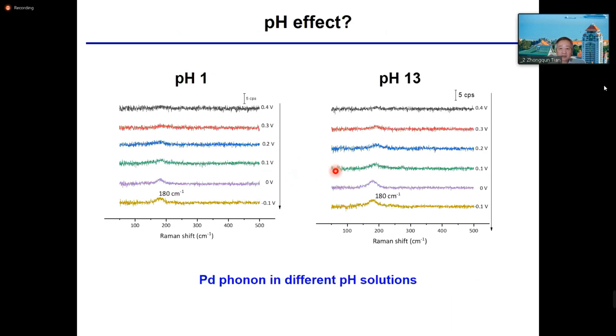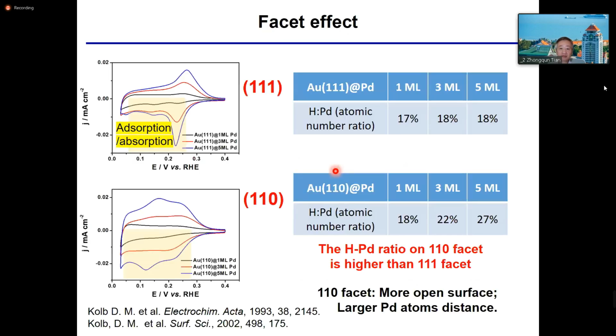But of course, as I mentioned, these are all very preliminary studies, and our students have been careful to recheck and do this experiment by several rounds in order to be sure that these peaks are real. But the assignment, I must say, we have not yet confirmed. As you can see, when we change the phase from gold 111 to gold 110, we can also see a dramatic change of electrochemical behavior in the underpotential deposition.